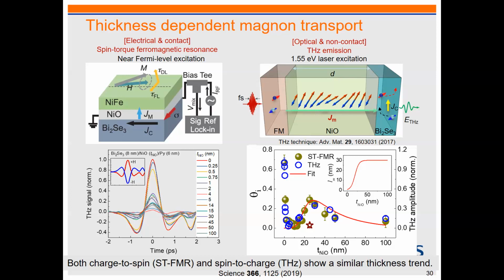So then, of course, the referee never believes it. How can you have this trend with 25 nanometer thickness? I don't believe it. So we had to do an inverse measurement. The inverse measurement is basically spin pumping. Because this is the forward measurement, meaning you inject charge current, which eventually changes to magnon and spin torque. Okay? So this is a charge to spin converter.